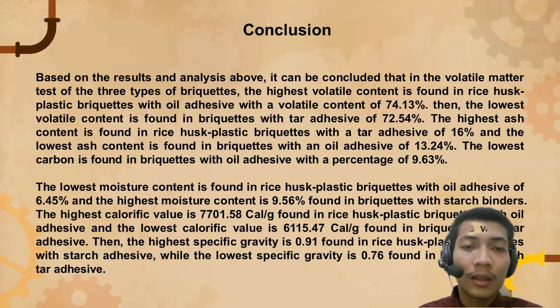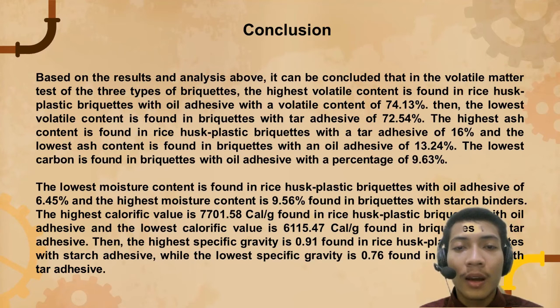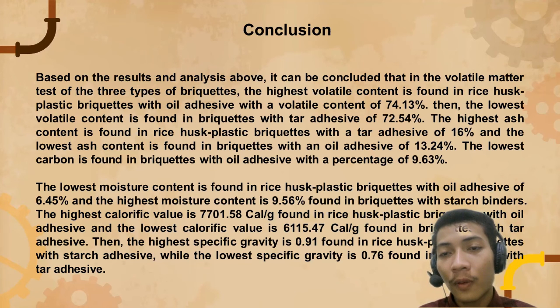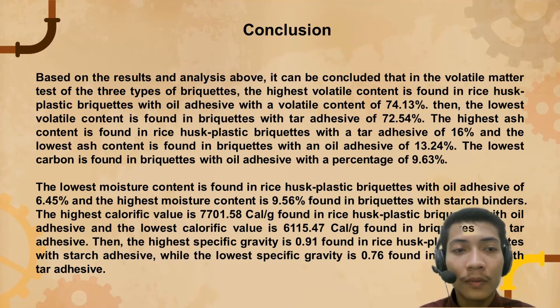Based on the results and the analysis above, it can be concluded that in the volatile matter test of the three types of briquettes, the highest volatile content is found in husk-plastic briquettes with oil adhesive, at 74.13%. The lowest volatile content is found in briquettes with tar adhesive, at 72.54%. The highest ash content is found in plastic briquettes with tar adhesive, at 16%, and the lowest ash content is found in briquettes with oil adhesive, at 13.24%.